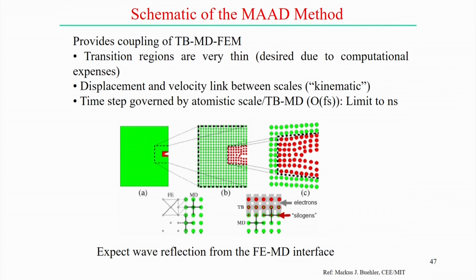So this is a schematic diagram for the MAAD method. If you see how it is coupling the tight binding, molecular dynamics and the finite element method, the transition regions are very thin, desired of course due to the computational expense. So displacement and velocity link between the scales based on the kinematics, and the time steps are governed by the atomistic scale, tight binding and molecular dynamics. That time scale generally follows the order of femtoseconds, but is limited up to nanoseconds. Expect wave reflection from the finite element and molecular dynamics interface, probably this method works well.